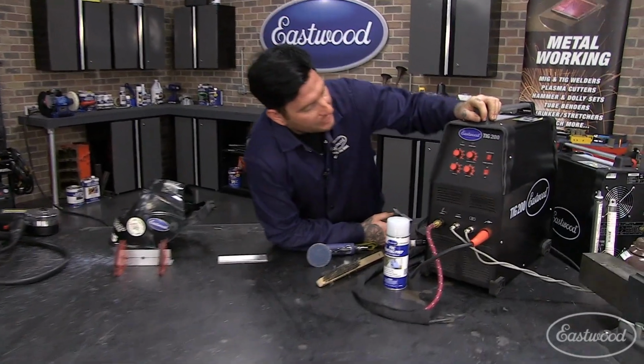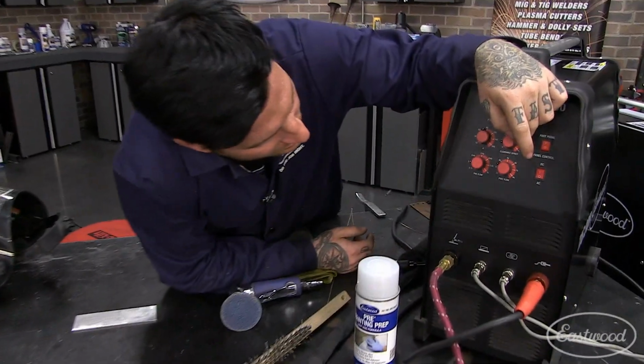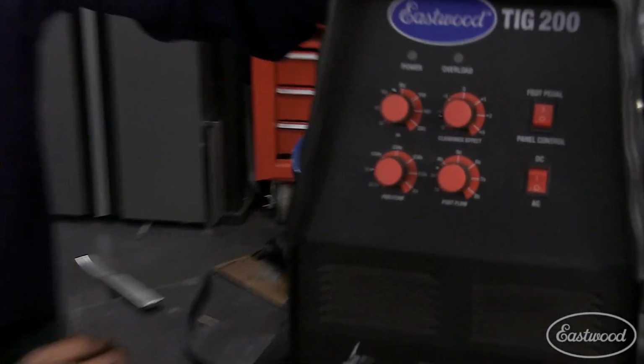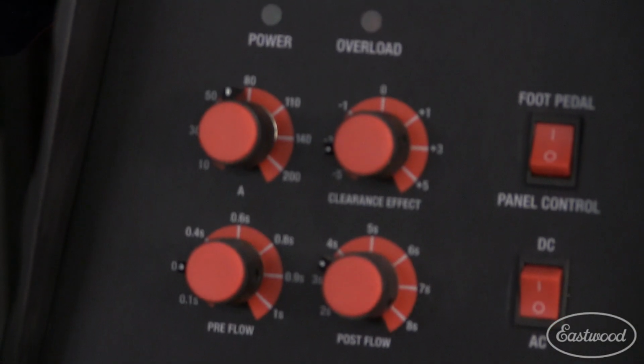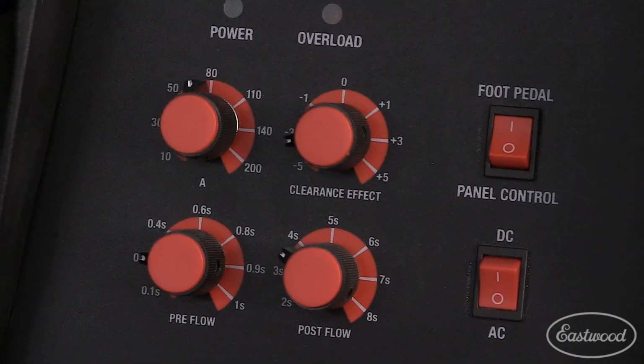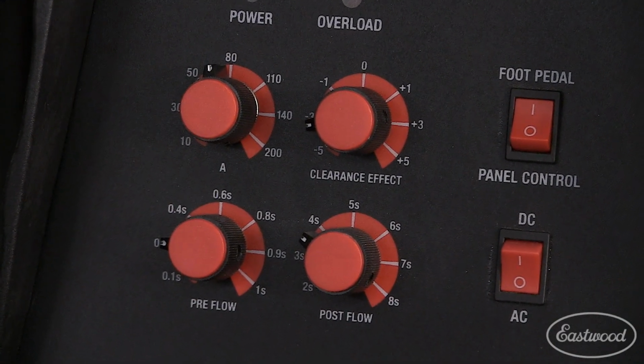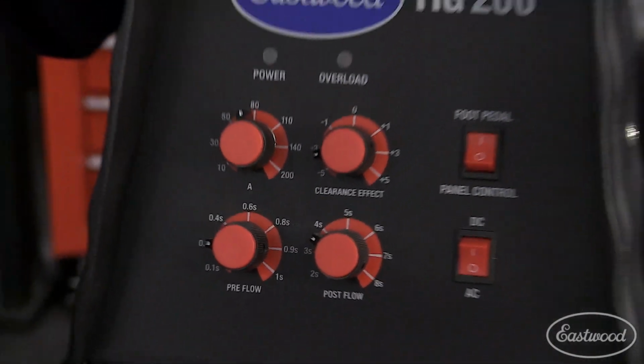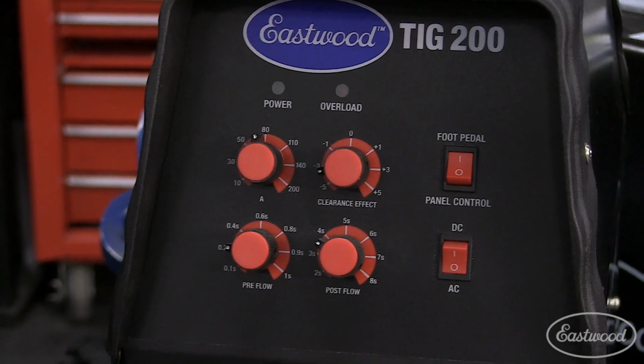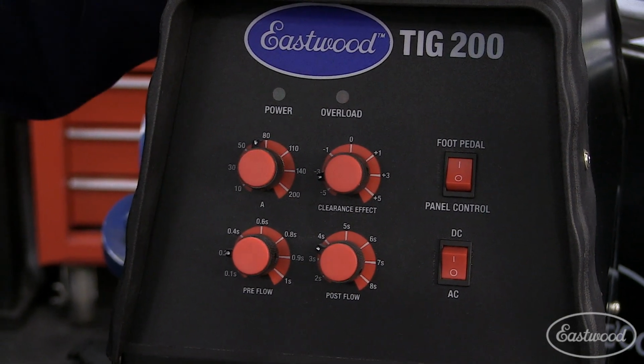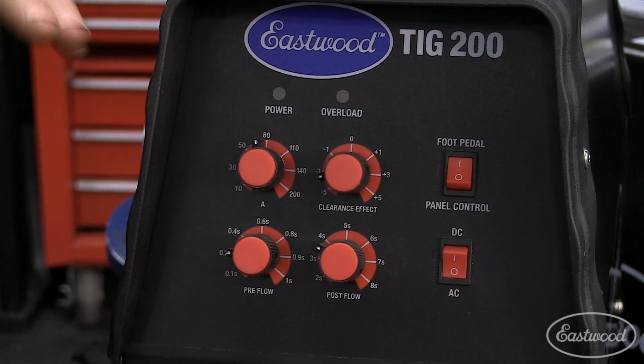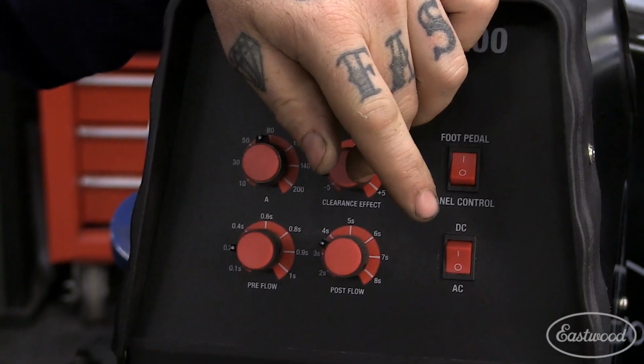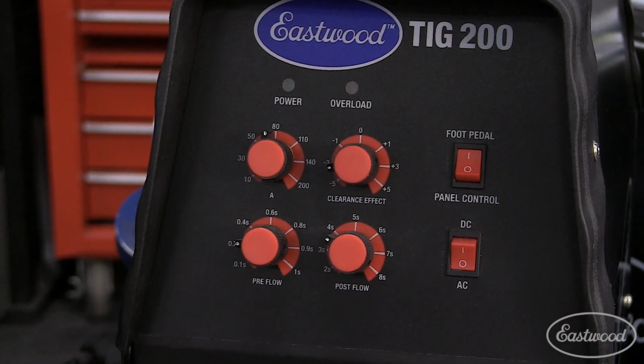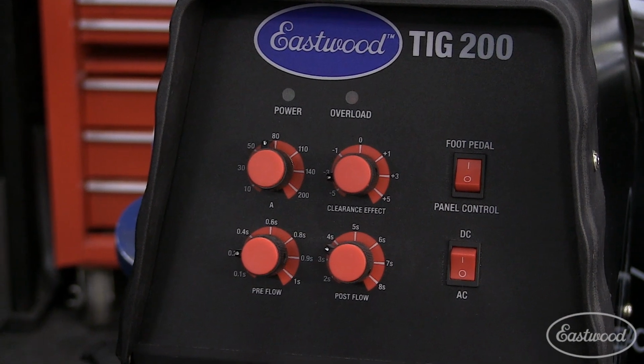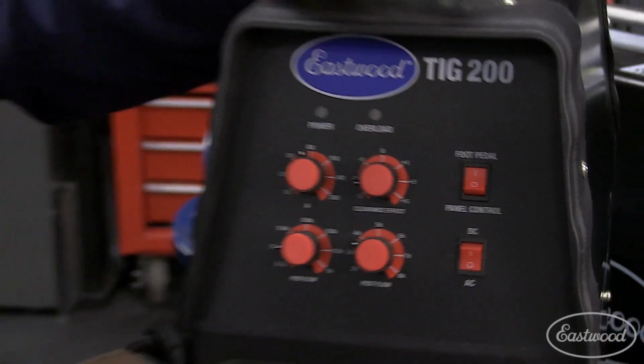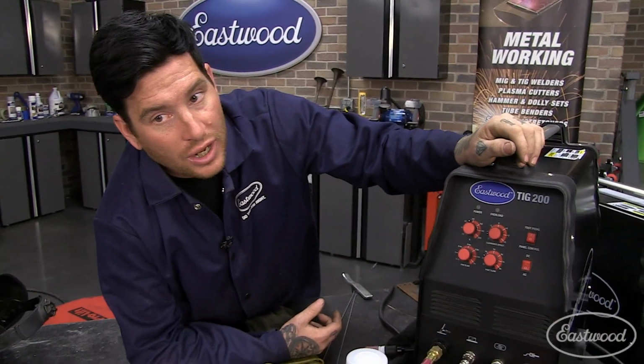The other dial that's pretty important here is the clearance effect. Some machines may call this a balance control. On our machine, it's called a clearance effect. Essentially, in a short version, you're changing the sine wave that's coming out of the machine, going from positive and negative. There's a sine wave going up and down. By playing with this dial, you can make the sine wave hang to the positive or the negative side, so it can hang for a split second or two longer.